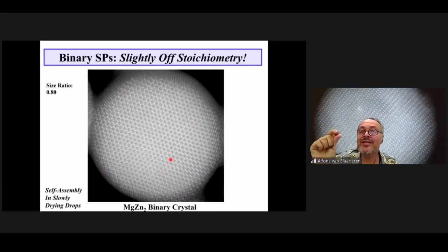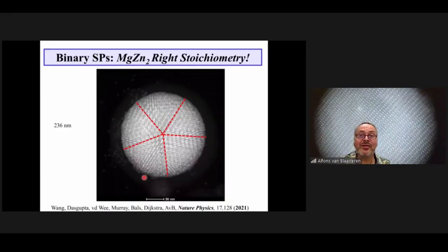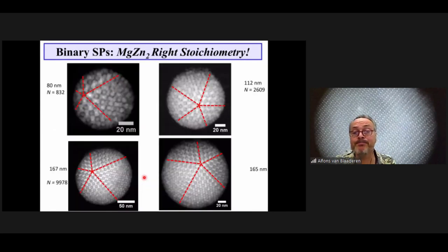What is very intriguing and very interesting as well for both fundamental studies and applications, if the stoichiometry is slightly off, so here there is a majority of smaller particles, then we get binary crystals, but not the icosahedral crystals. So we have an idea why that is, but we can discuss that perhaps also if there are questions about that. But if the stoichiometry is right, then all the superparticles with a size of about a few hundred nanometers, so 100,000 nanoparticles again, become icosahedral.